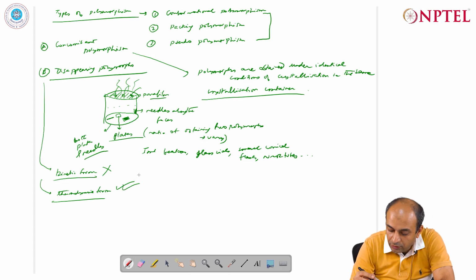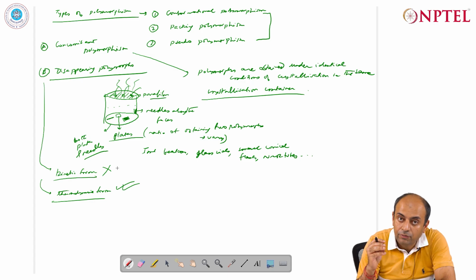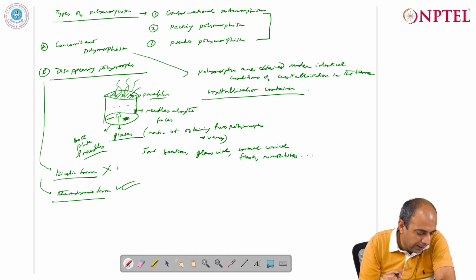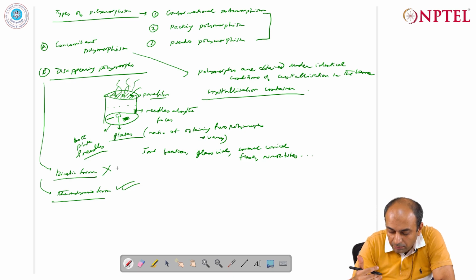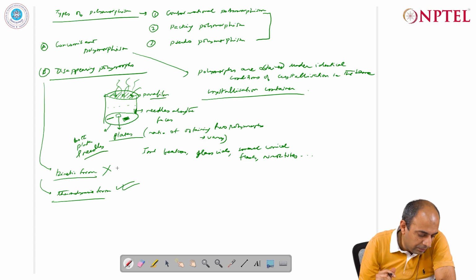So the ability to isolate and characterize the kinetic form becomes extremely difficult, and this has very severe implications in the pharmaceutical industry, and these are some of the things we will explore later. The kinetic form has the higher Gibbs free energy, therefore it is more easily available in terms of bioavailability, it can have a higher dissolution, and therefore the overall pharmacological property of that polymorph can be compromised if you do not have the kinetic form but have the thermodynamic form, because the latter is much more stable and might have a reduced solubility compared to the kinetic form. So it is very important to be able to get the desired kinetic form, but if you do not get it, then that particular form becomes the disappearing polymorph.